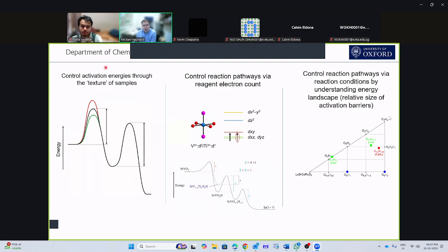So in the first story we saw I can control the activation energies in the system by the texture of the sample, so the particle size and the strain. We can control the pathway followed by the electron count. And we can also control the pathway by looking at the relative size of the different activation barriers for the different processes and adding different reagents, so either having hydrogen present or not.